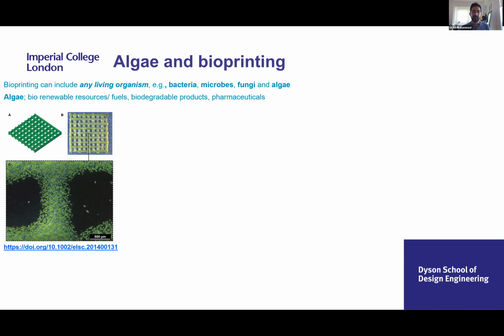So some studies that have already looked into 3D printing with algae include the study which looked at the co-cultivation of microorganisms in close contact with microalgae, and this was to improve the oxygen supply of different cell types by photosynthetic oxygen evolution. This was achieved by bioprinting immobilized microalgae embedded in hydrogels and subjecting them to either direct continuous light or light-dark cycles. They measured their sustainability and their viability through flow cytometry and fluorescence imaging.